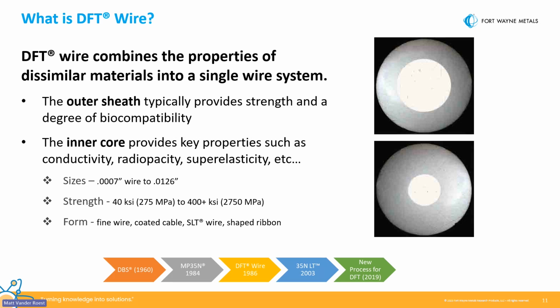Where this originated from, down at the bottom, you can see that Fort Wayne introduced a material called DBS into the industry in the 60s. And basically DBS is where we took like six wires of stainless steel that were wrapped around a core of silver. That strand was then brazed, which allowed the silver to proliferate amongst the different stainless steel filars in that strand. And that improved the conductivity. So we were taking the fatigue and the mechanical properties of stainless, joining it with the conductivity performance of silver. And that DBS material was drawn to final size and used in many different CRM applications.